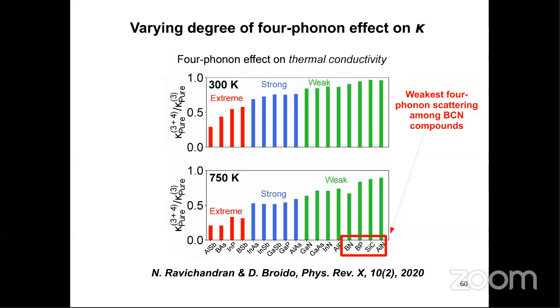So if you look at the left-hand side, aluminum antimonide is a very large mass ratio compound, and does not contain boron, nitrogen, or carbon. So you would expect with these rules that the effect of 4-phonon scattering will be strong. So it will give you a good picture, but of course, if you want to get very quantitative results, you have to do the full calculation. Sure. Okay. Thank you very much.